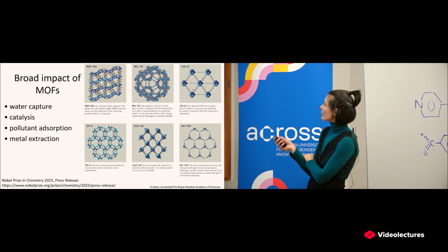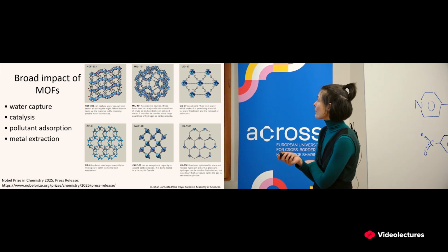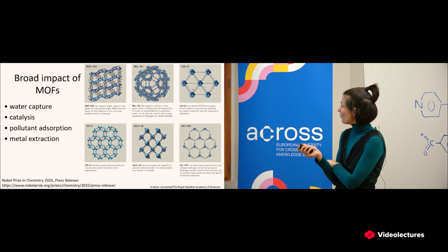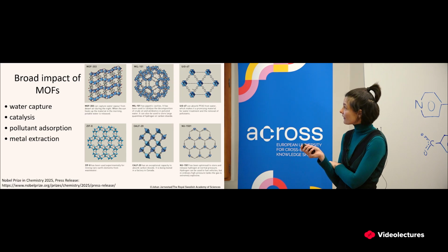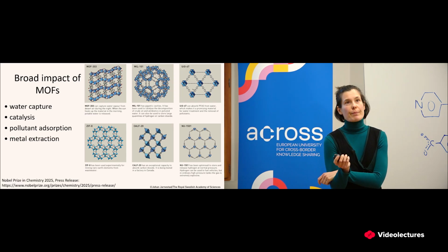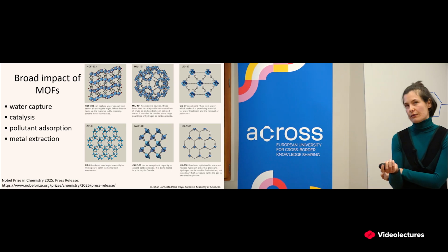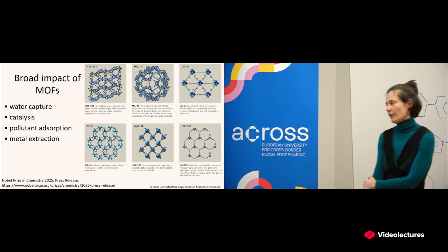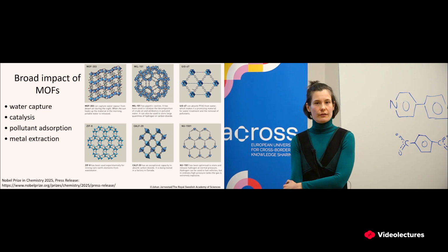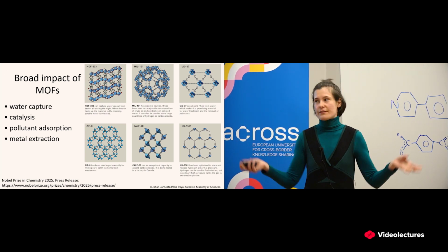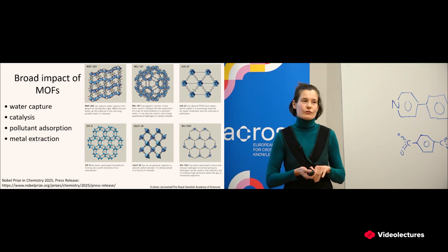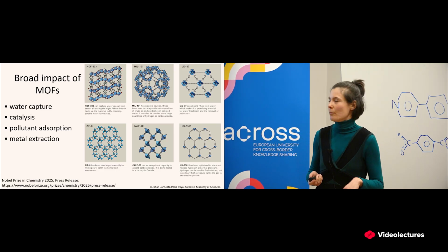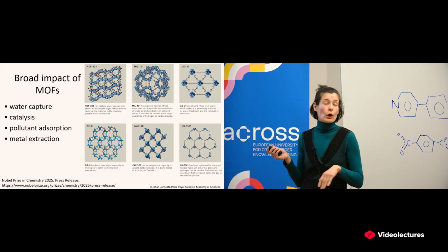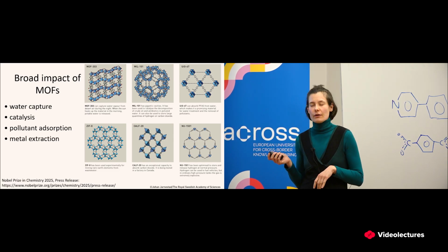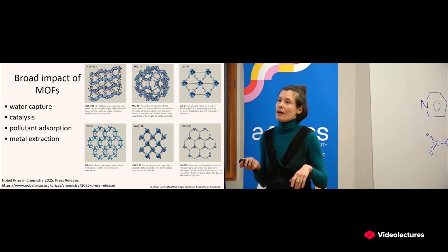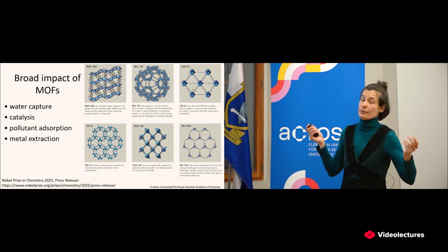The pollutant absorption one is actually this one, which I skipped, UiO-67, which has a hydrophobic linker, this biphenyl moiety that you see here, and a zirconium cluster. And so because of these biphenyls, the structure is quite hydrophobic, so it can form interactions with, for instance, perfluorooctanoic acid and the other PFAS molecules. So these are fluorinated molecules that are quite toxic and shouldn't be present in drinking water. There are strict limits as to how much is allowed. And then the zirconium metal cations in the structure also form ionic interactions with carboxylic acid functionalities in PFOA, for example.